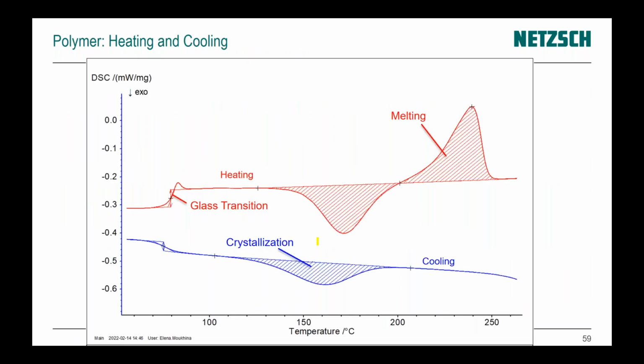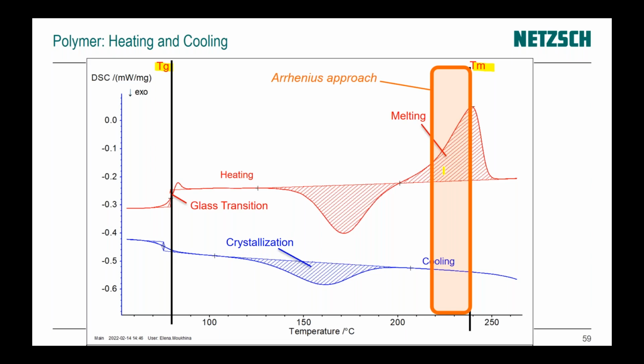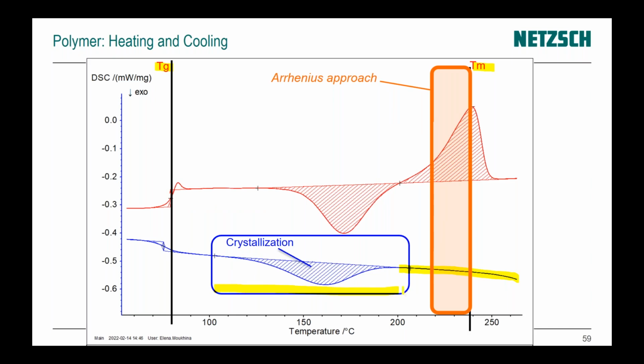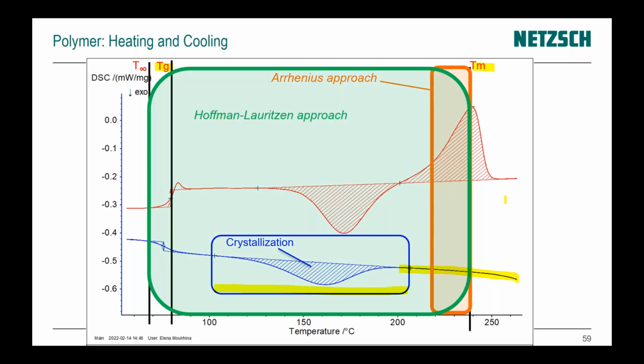If we make heating and cooling, then we have glass transition and melting. The Arrhenius approach shown just now works only here, for isothermal crystallization. But if we have real cooling, crystallization happens here, outside of the Arrhenius approach. Therefore, we should use a non-Arrhenius approach.